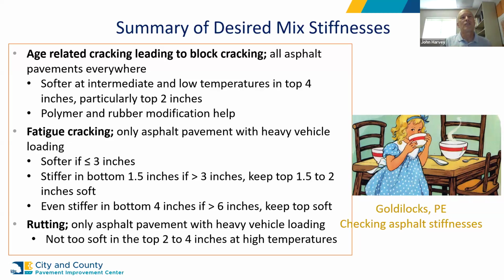Polymer modification, using polymer modified on the surface or rubberized hot mix are both great for dealing with age-related cracking because they're nice and rut resistant at higher temperatures, but they stay nice and soft at the intermediate and low temperatures. That's what the modification does. For fatigue cracking, and again, this is only where we have the heavy vehicles, we want to keep that softness for the age-related cracking, but not so soft that we get rutting. We want kind of a Goldilocks